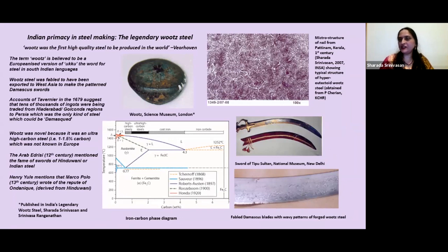If you look at the composition of wootz, which had about 1.5% carbon, you see that it consisted primarily of a matrix of pearlite surrounded by cementite. In fact, the microstructure of a nail from Pattanam that you're looking at above has exactly that classical composition of wootz, and that is one of the early examples. The speciality was that the ingot of wootz was forged out, and you get alternating layers of pearlite and cementite, which gives a wavy pattern when it's etched, known as the damask, which was prized by the Arabs, and that's why it was exported.